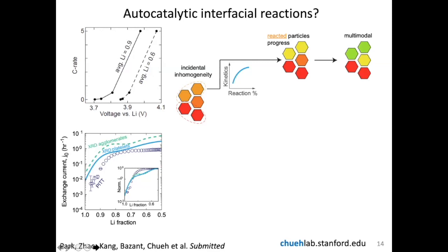So by autocatalytic, I mean that as you remove lithium, the exchange current density is getting higher and higher. This is very similar to the diffusion coefficient, whereby as you remove lithium, the kinetics of the particles gets better. So this is what I'd like to show you here. We have a schematic of particles which have incidental inhomogeneity. This could be due to different particle size, variation, and coating. And what I want to see here is how this heterogeneity amplifies or decreases as you remove lithium.